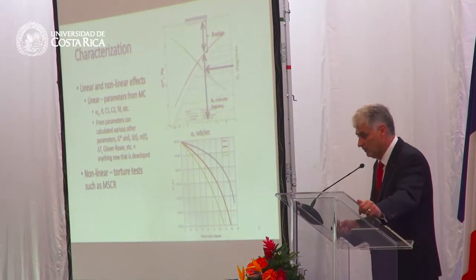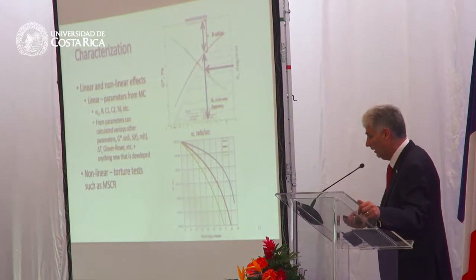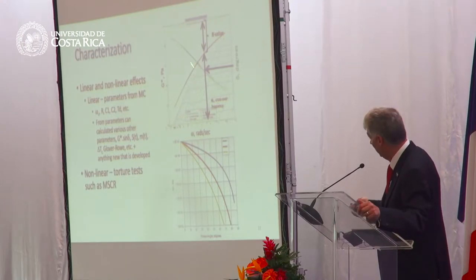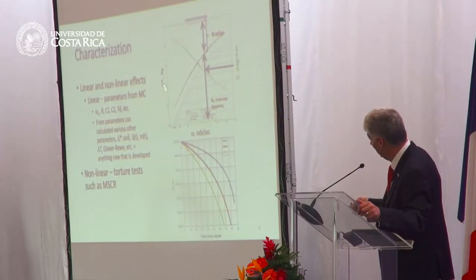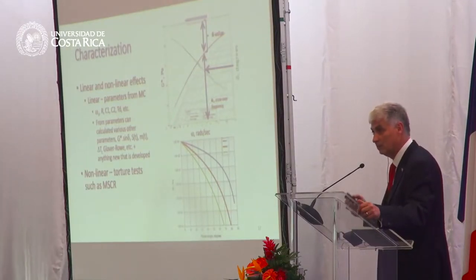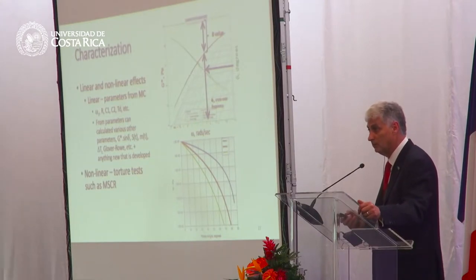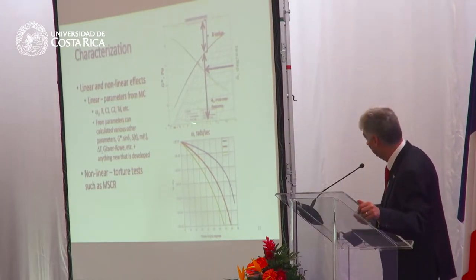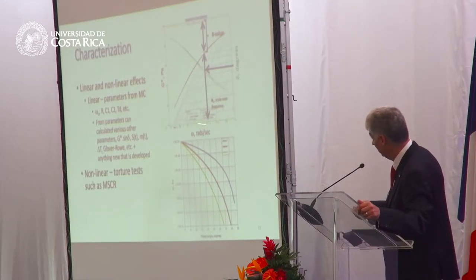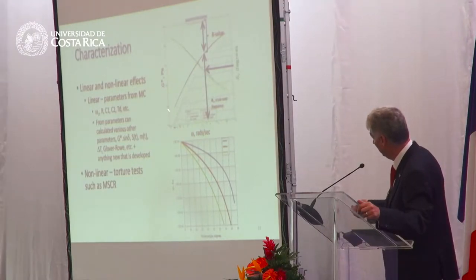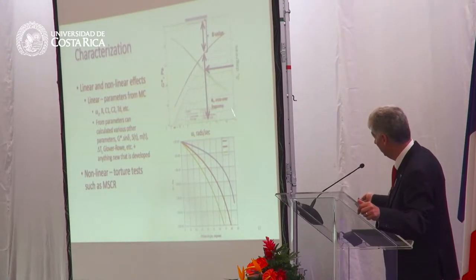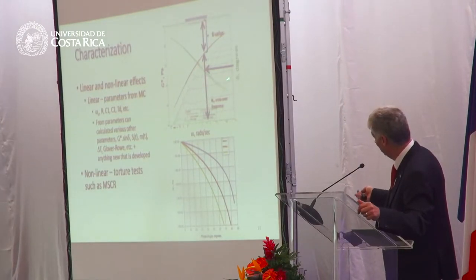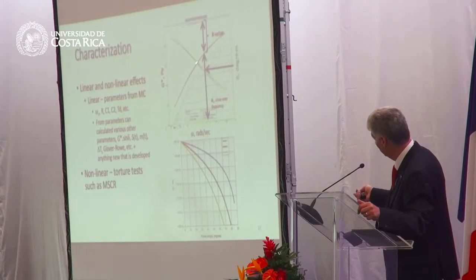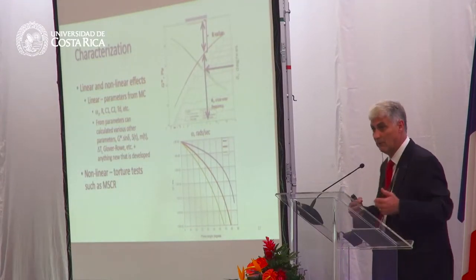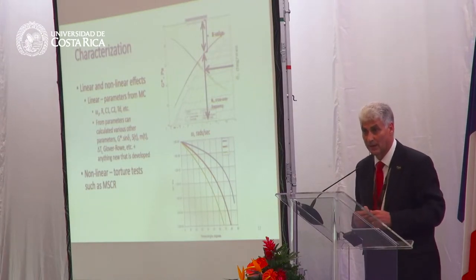I want to take a couple of minutes and explain what we have on this graph. This graph here on the top right-hand side shows a master curve. On the vertical axis here, I have the complex modulus. This is really the stiffness of the binder, the stress divided by the strain, the stiffness of the material. Here I have frequency, which is the speed of loading. So that slow truck going up the hill would be down here. Fast traffic would be over here. Here I have the phase angle. So this green line is the phase angle. This one is the complex modulus. The phase angle is how much viscous behavior is captured in that asphalt binder.